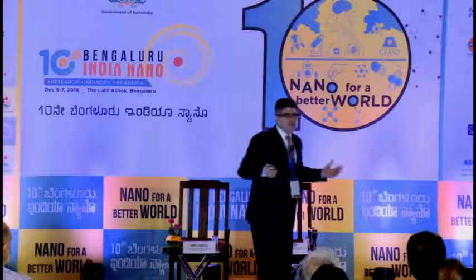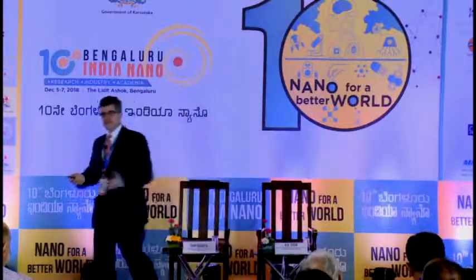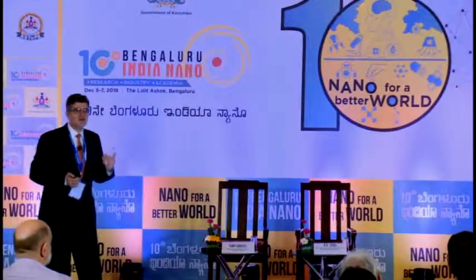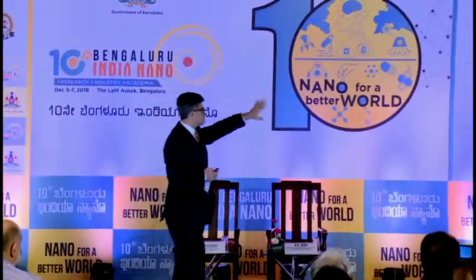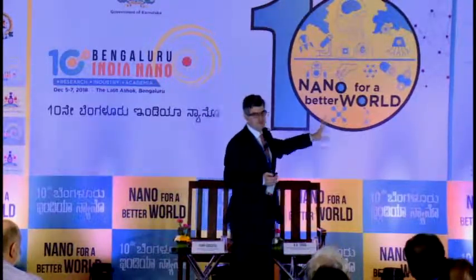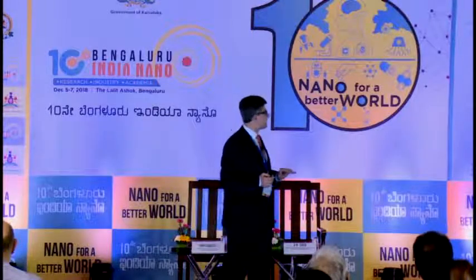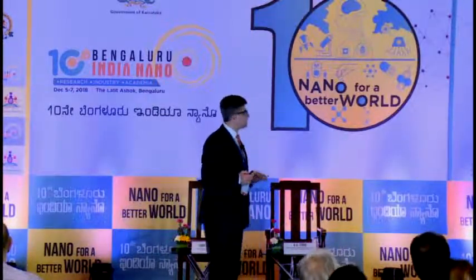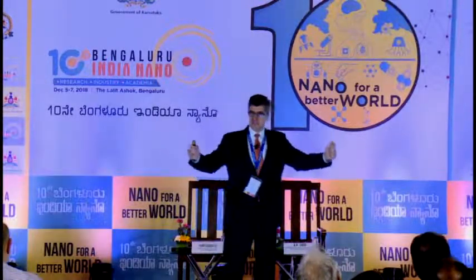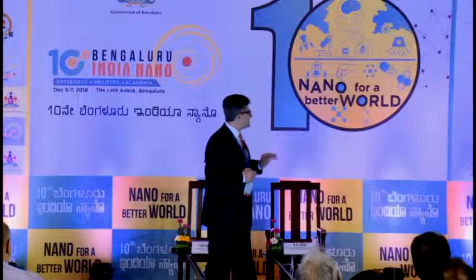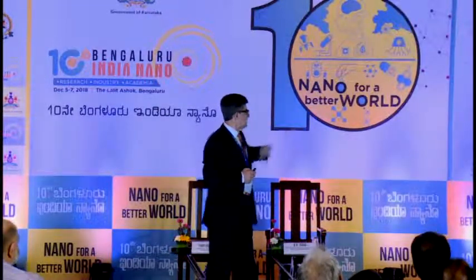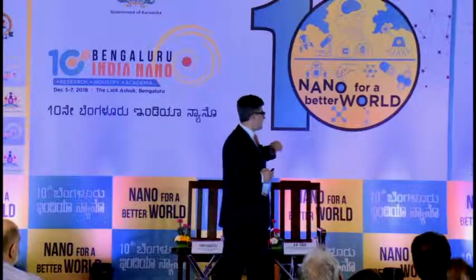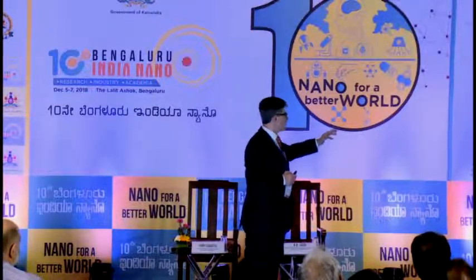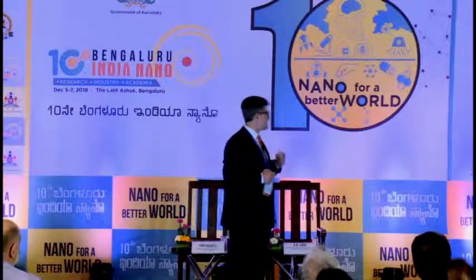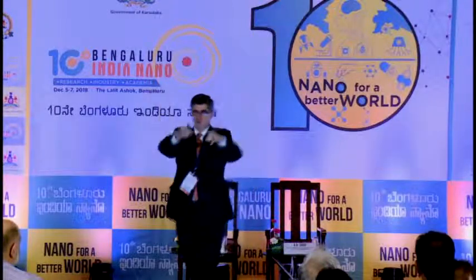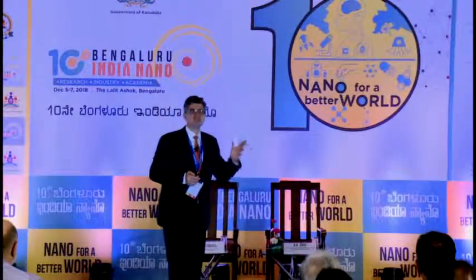And why are these materials good? I talked to you a lot about how we can make them. There are many of them here. But they do really have a variety of very interesting properties. First of all, with no surface termination, all of them would be metals. But surface termination can open the band gap. For example, oxygen termination can open a band gap in M2C MXenes because it can pull electron density away from a thin structure, especially here. Many interesting properties have been predicted here. For example, topological insulators, quantum spin Hall phases related to it. Very high work function on some of the materials. Chemically tunable superconductivity. Dirac fermions, so cones like in the band structure of graphene, and others as a function of composition.